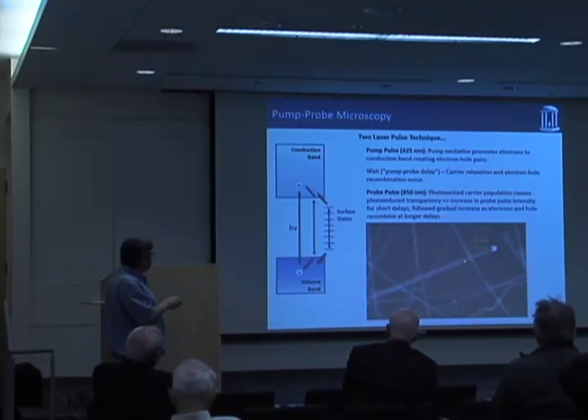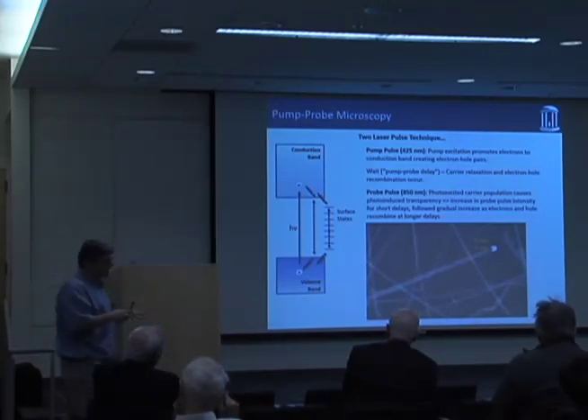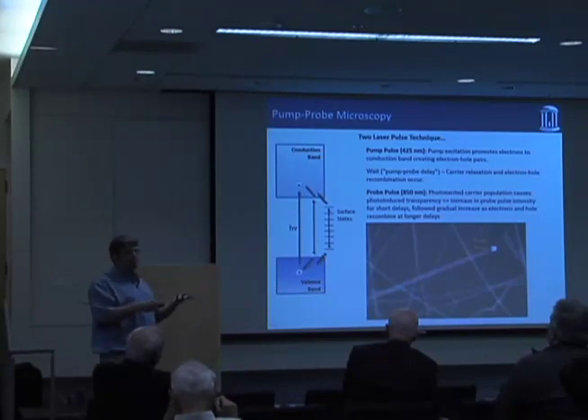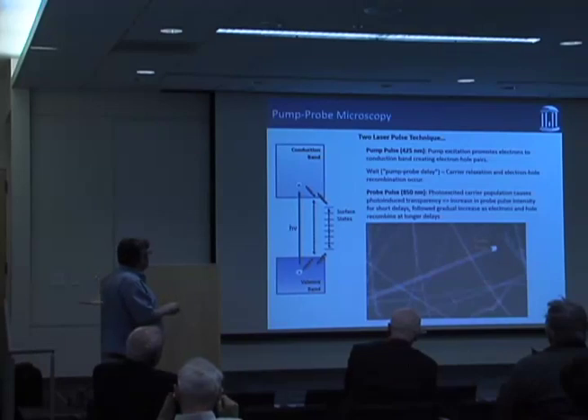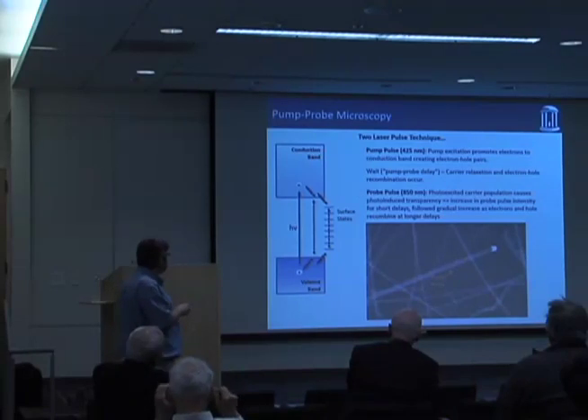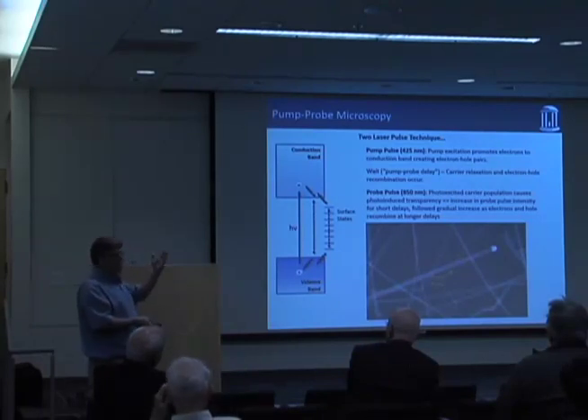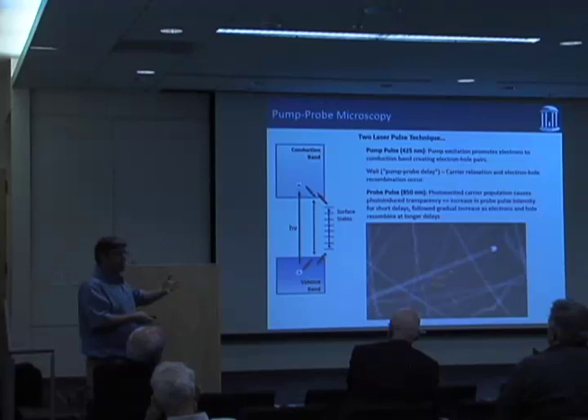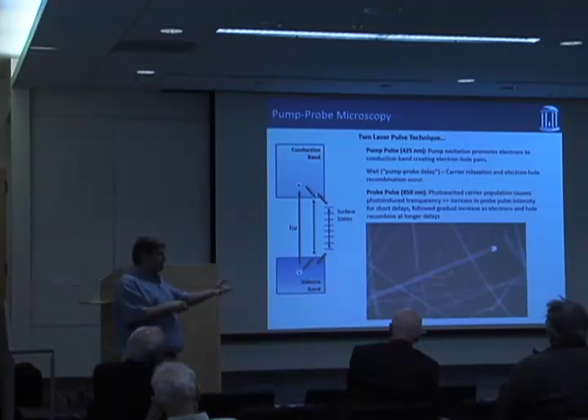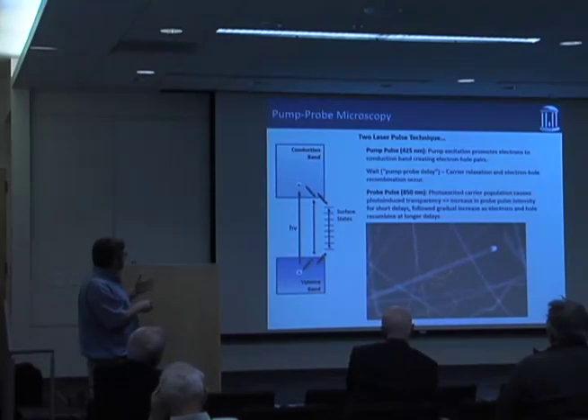And in that region where it excites the sample, it's going to create a whole bunch of electron-hole pairs, somewhere in the neighborhood of maybe 50 or 100,000 electron-hole pairs in that focused spot. The pump pulse is going to go away, and then we're going to come along later with a probe pulse at 850 nanometers, so it's out in the near infrared. And in silicon, it turns out that when you put carriers in the conduction band, or you photoexcite silicon, it becomes more transparent. And so a little bit more of the probe beam will pass through the sample and be detected by our detector. So what we're going to do is look at the change in intensity of the probe beam with and without the pump. And when you have carriers in the conduction band, the intensity of the probe beam is going to go up a small amount.